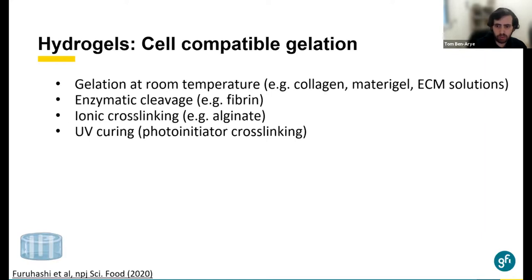The ions used here are calcium, which is a little bit toxic for the cells, but maybe that's okay if we don't use too high concentrations. Another option is UV curing, using photo-initiators. UV light is also a little bit toxic for the cells, and the photo-initiator is also a little bit toxic, but researchers say that that's okay. You don't use too much time, you don't do it for very long, and you use low energy UV light, so that's perhaps not that bad. But this is another valuable approach in order to generate gels.